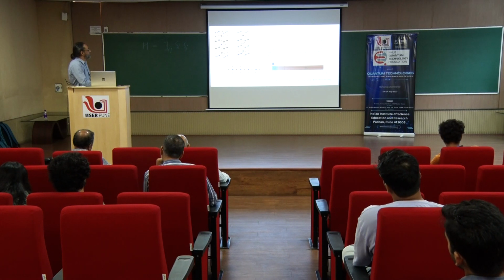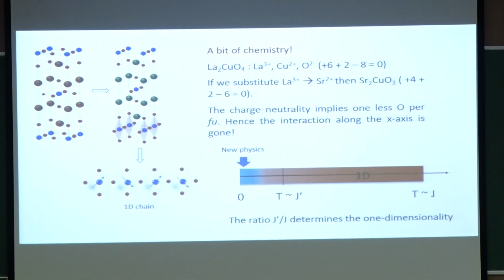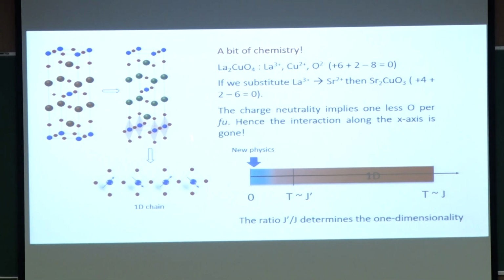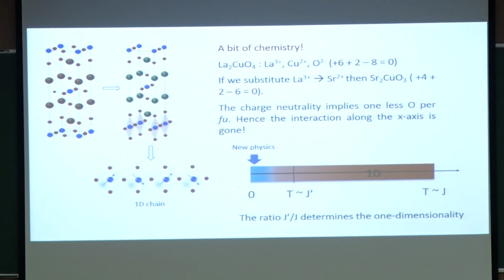But besides that, there is also an interchain interaction. The interaction which exists between the copper spins in this chain and the copper spins, for instance, in this chain. If I complete this unit cell, you would see a chain forming here as well. All right. So, this interchain interaction is called J prime, and the interaction that exists within the chain is called intrachain interaction, and I will depict it throughout this talk by J. So, how good the one dimensionality of your system is determined by the ratio J prime by J. If J prime is 0, then of course your chains are completely isolated, and then you have a very good one dimensionality. On the other hand, if J prime is J, you have recovered the 3-dimensional case.